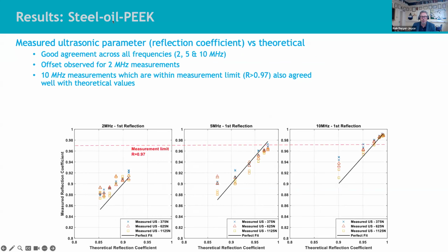Now it's steel, oil, PEEK. So now what we're doing is not steel, oil, steel, but the more realistic case of steel, oil, PEEK. Does it behave as well? Well, it's not quite as easy now, because PEEK has a different acoustic impedance, that's that term Z, than steel, so it becomes a little bit tricky to measure, but you can still do it. We get good agreement across.